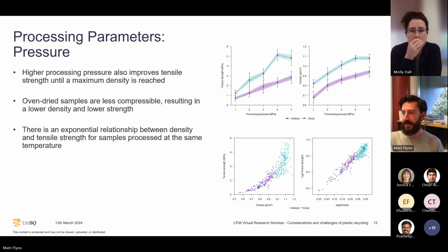Then we have the pressure that we're using to press it. So as you can see in the light blue here, the samples get up to a certain density here, and then they plateau. They don't get condensed any further than that, and this is where the tensile strength plateaus as well. When the samples are dried, they don't condense as much, and so they don't have this plateau, but we have a really nice exponential relationship. So you can see on this log-log plot that it becomes linear when it's plotted this way. So there's a really close relationship between the density of these samples and the tensile strength.